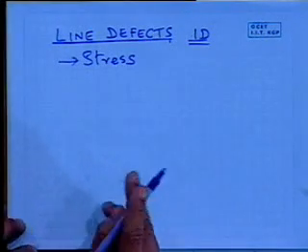A very simple example: if you take a wafer of silicon, very clean, pure, hardly any defects in it, and in the process of handling it, you hold it with a tweezer, a metallic tweezer. So this is my nice little silicon wafer, and I put the tweezer on it like this to take it somewhere. Right under where I put the tweezer, we've gone and generated a host of dislocations. Because there is a formation energy of dislocations for different materials. If it's a softer kind of material, just the very act of pressing it there to take it from here to here, I've already gone and destroyed it. So in commercial processes, nobody will be sitting there handling it with tweezers.